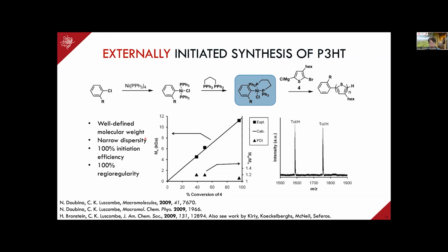Other factors is that by incorporating this initiator, we start to be able to control the end group that we have in the polymer. And what the MALDI spectrum down here shows is that using this system, we have one set of end groups. So it shows that our initiation efficiency is 100%.